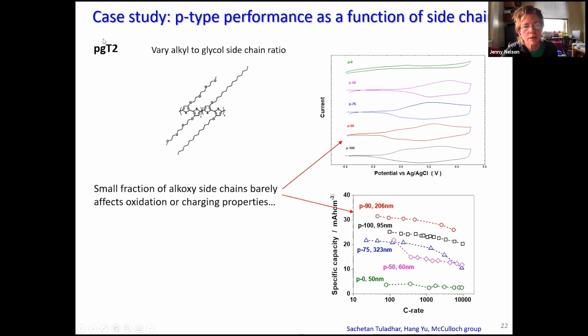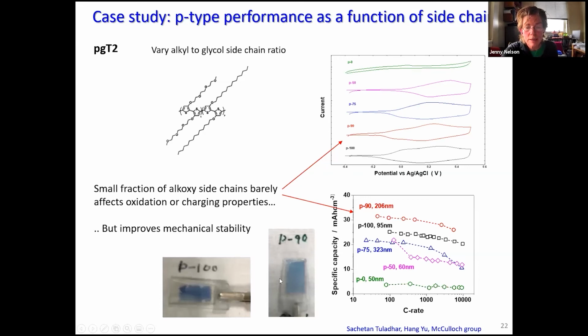So we decided to avoid any issues to do with working in oxygen. We decided to look at the same problem in the case of a p-type polymer. And we looked at a series of p-type polymers with a different fraction of alkyl and glycol side chains. And the interesting thing we have observed is that when we have replaced a small fraction, 10% of the glycol side chains with alkyl side chains, alkoxy side chains, this doesn't have any negative impact either on the oxidation potential or on the specific capacity. They work more or less just as well, but in terms of their cyclability, they're much more robust to repeated cycling.